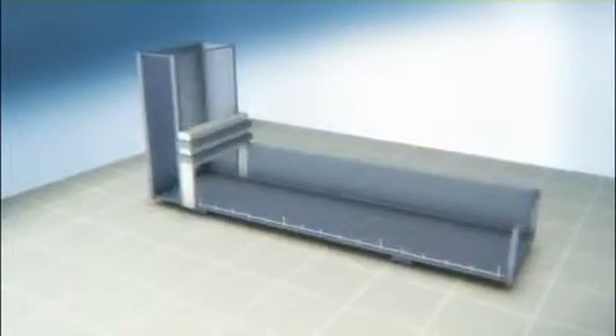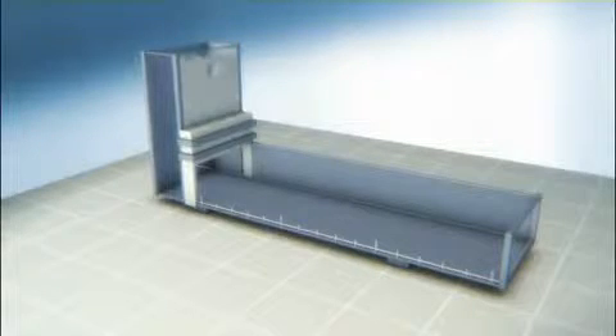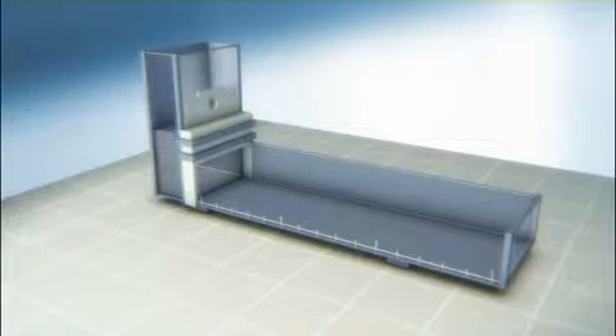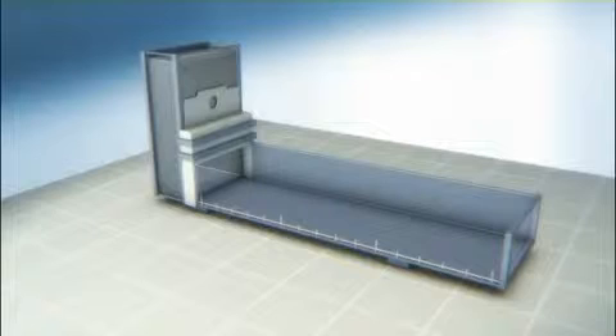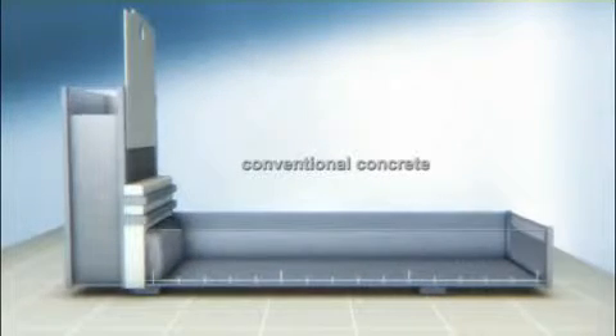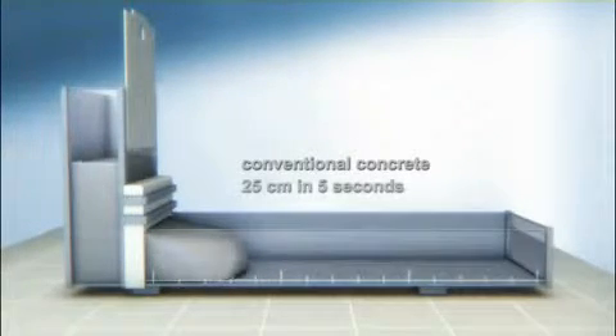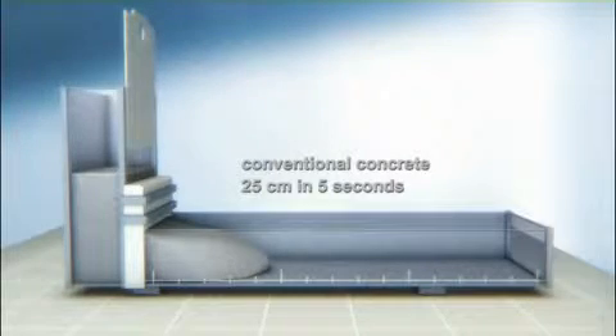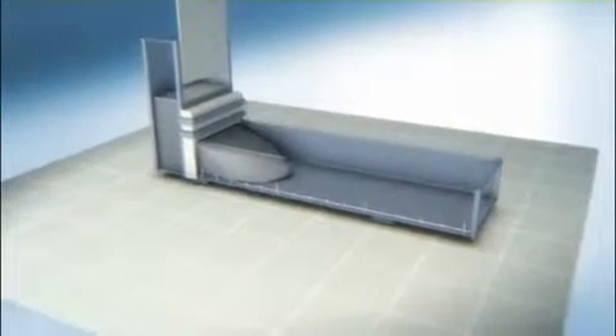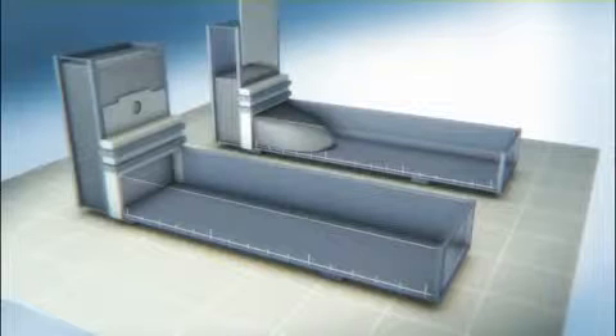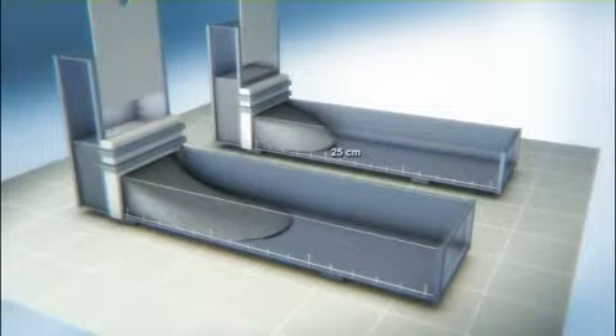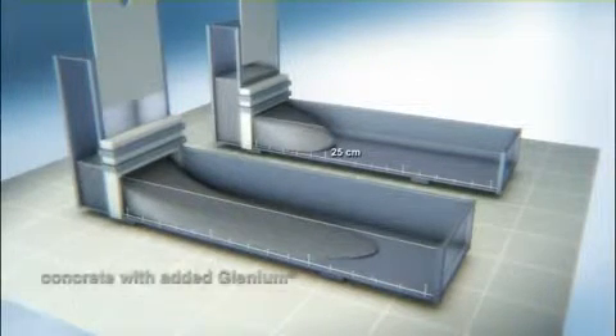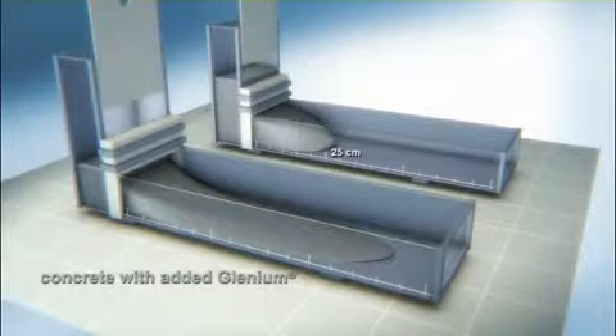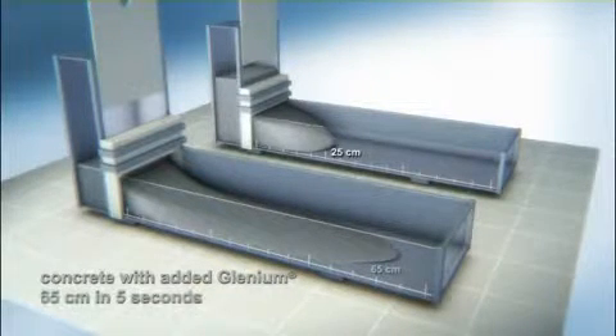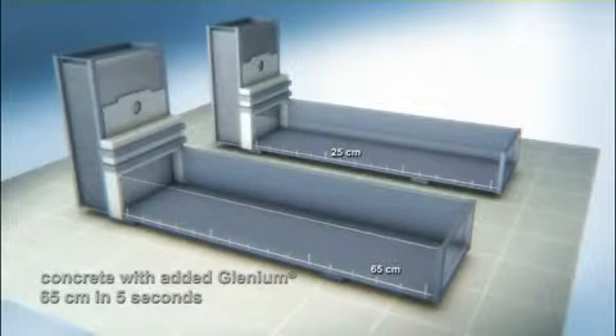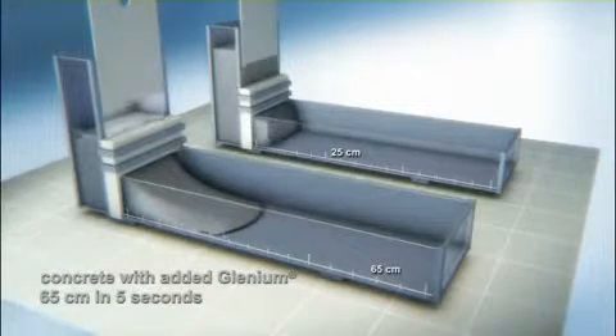A pilot plant comparative study between conventional concrete and concrete with added Glenium, but with the same water content and mixing ratio, clearly shows this. With conventional concrete, the flow process already stops after 5 seconds and after a distance of about 25 centimeters. Concrete to which the superplasticizer Glenium was added flows much faster, and the distance travelled over the same period is about 65 centimeters.